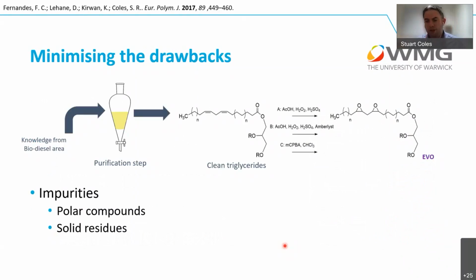So our first step was to just purify it and do some simple purification and epoxidation steps. And the purification step, we literally stripped straight from biodiesel production. It was exactly the same process that we used there. So you take the waste oil, effectively filter it to remove out any of the lumps of burnt food and debris that are in the oil, and then add a very small amount of water. If you add too much water, you start to have the potential to produce soap, so you keep that down to a very minimum, but you do a small amount of water quite a few times in order to remove the polar compounds that you've got.